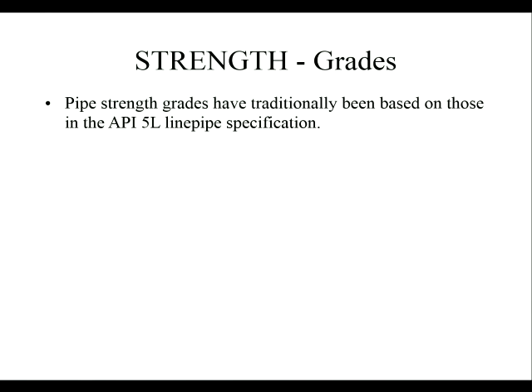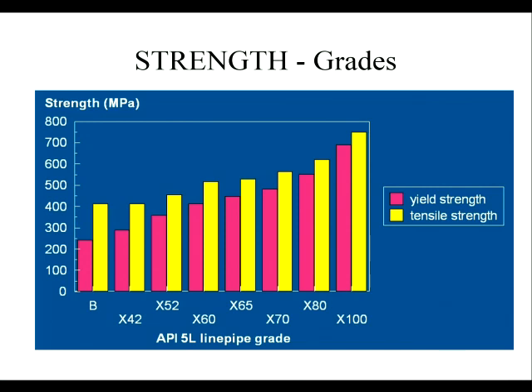Right. How do we define the materials then? Well, the American Petroleum Institute, API, has a standard line pipe specification. It's the 5L specification. And there are various different grades of steel that can be used to make line pipes defined in this specification. And here is an example. You can see grade B, which is really water pipe, is where things started up, and then the X grades go upwards. And if you look at that, the tensile strength goes up a bit, but there's an almost linear increase in yield strength. And there should be, because the grade, the number after the grade, is the effective yield strength in KSI, or 1,000 times PSI. So it should be proportional because that's the way it's been defined.